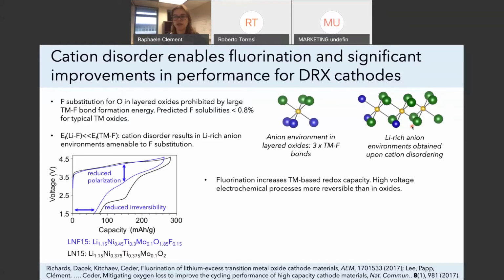Why is fluorine substitution an important factor for these materials? Well, what we found here, and this is a work that was comparing 2 cathode materials, both of them have very similar chemistries, but one is an oxyfluoride, so we've substituted some oxygen, the other one is a pure oxide. And if you compare the performance of these materials, and these are not the best performing materials, by the way, this is just an example, but this clearly shows you that you have reduced polarization as you substitute with fluorine, and you have reduced irreversibility.